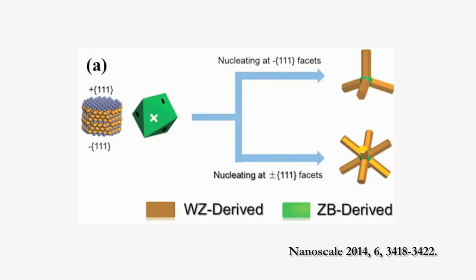Normally, a solid will occur in one or other crystal form. However, in some cases these polymorphic forms can co-exist in a single particle, giving rise to what is termed polytypism. These polytypic crystals have one or more interfaces shared by these crystal structures, which gives rise to a new stacking sequence such as ABC-AB or AB-CBA.